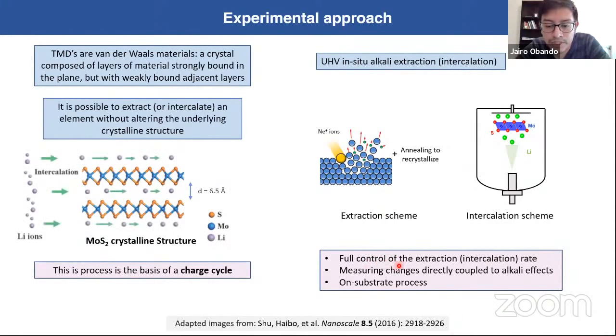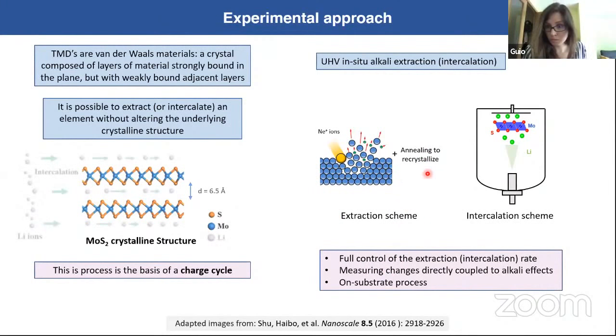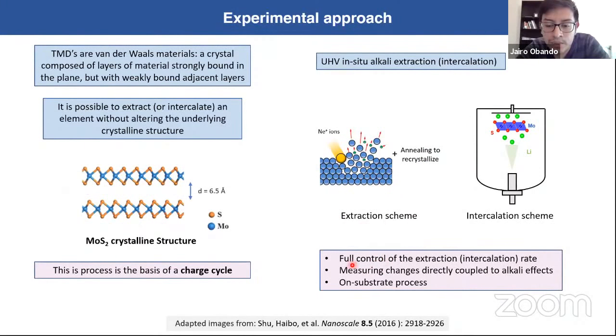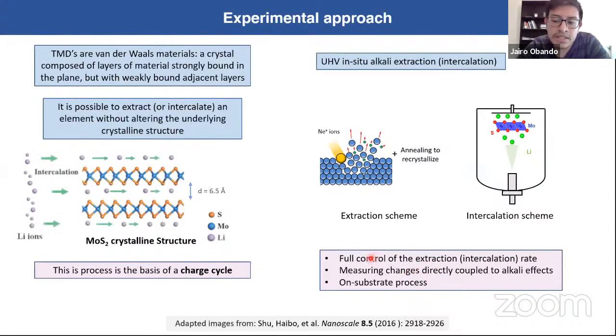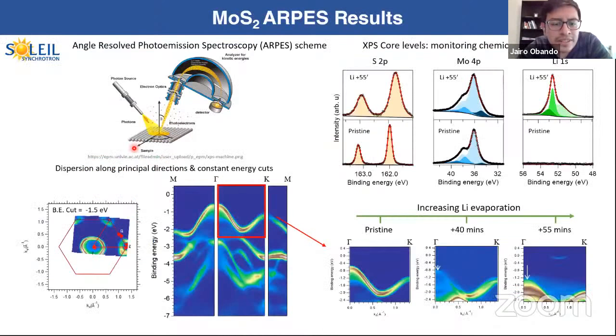It is also important because, as these techniques happen in an ultra-high vacuum environment, it allows us to measure directly the changes and couple these changes to the inclusion or extraction of alkaline materials. To observe the changes in the electronic properties, we use angle-resolved photoemission spectroscopy, which allows us to reconstruct the band structure of the material and to observe subtle changes in the valence band. Here you can see a cartoon of the ARPES technique. Knowing in detail this region, the valence band region, as well as the evolution of the Fermi level is crucial, because this is how we can quantify the electronic interactions of the material with respect to an external agent.